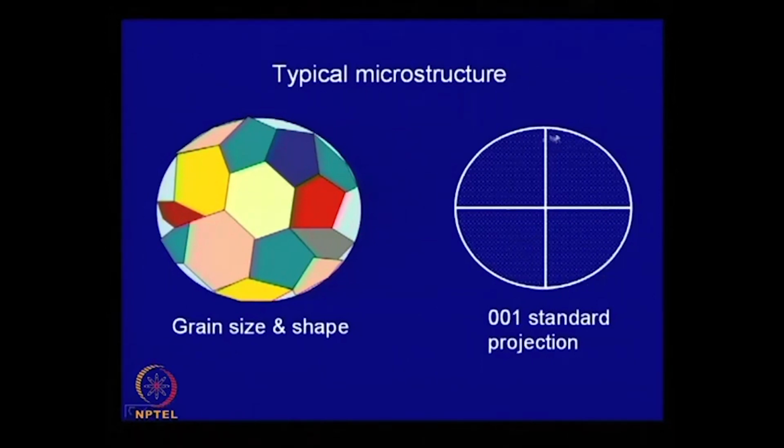So, basically they will be uniformly distributed, whereas if there is a preferred orientation, if somehow you can control the solidification so that it forms almost a directionally solidified structure, then it is possible that all the cube axes may be located here, along this, along this, along this. So, you will have more density of such poles in these areas, whereas these portions will be vacant, with no poles pointed over here.